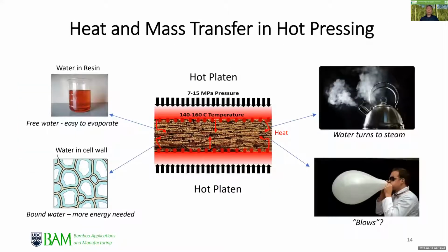And if you look at the pressing itself, there's a lot of consideration to be given to the moisture aspect. There's moisture in the wood as well as in the bamboo, as well as moisture in the resin, and that moisture under high temperature and pressure conditions can create a lot of steam pressure that can cause blows or delamination.